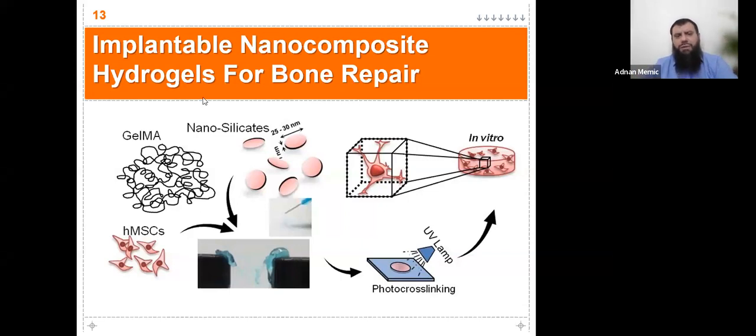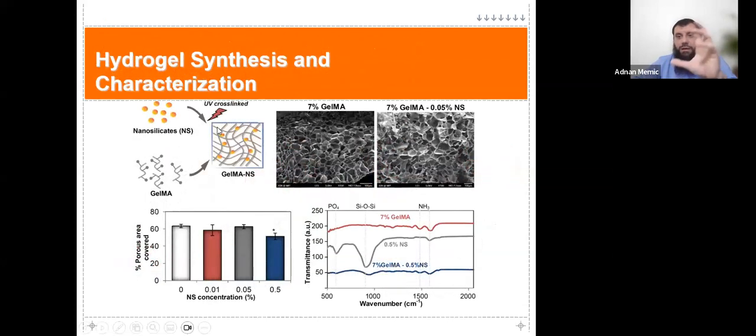But if we throw in these nanosilicates, Laponites specifically, they have a unique structure. They have very negatively charged sides, and then you have positively charged, I think, the rings around it. So with this charge distribution, you start to generate unique properties. And what you can do is that essentially with time, you can get that stem cell to commit into an osteo, into a bone type of lineage. So you can take a stem cell and get a bone cell afterwards.